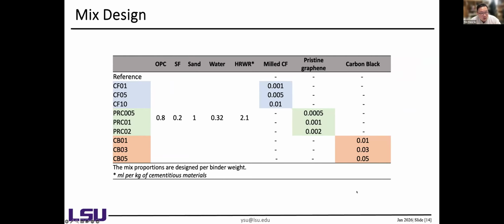So then we first came up with the mix design. We use ordinary Portland cement, silica fume, sand and water to make the mortar because we want to target 3D printing and pilot testing first. And we add the milled carbon fiber, the pristine graphene, and the carbon black, to see which is better in terms of different properties.